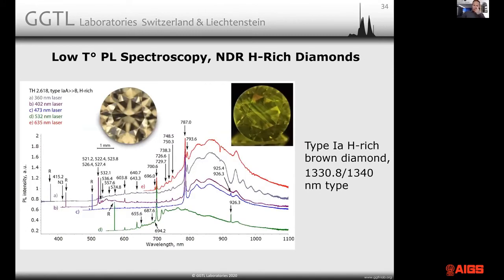Let's look at the PL of such stones. The PL color can be somewhat variable from stone to stone. Here we see a greenish yellow PL from this broad band back here with the different features at 522, 527, and all that. And the strongest features of these stones are the 700.6 nanometer zero phonon line and its vibronic, and 787 and 793. A lot of what we see here is, like with the other sample, nickel related. So nickel is a very common thing in hydrogen-rich diamonds.